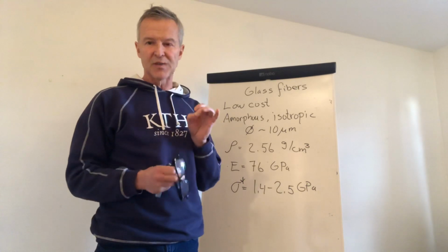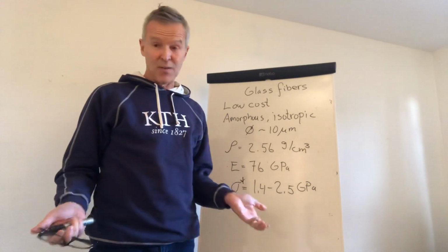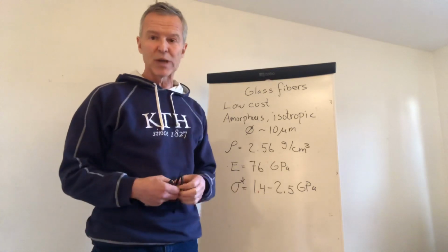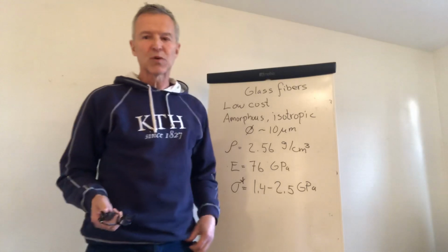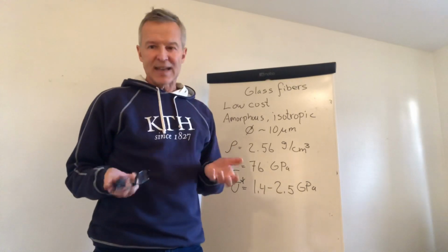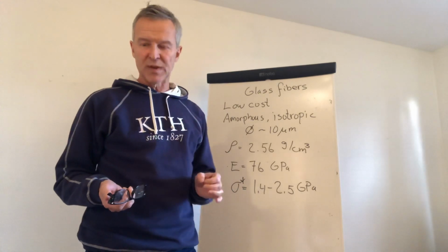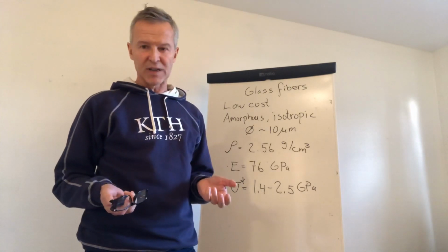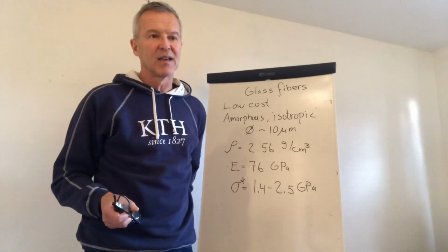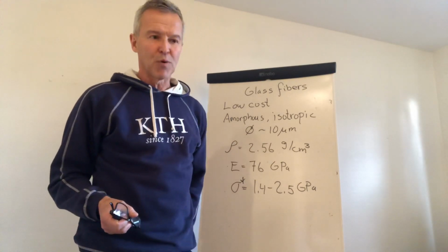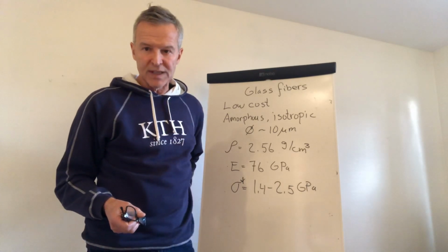So the intrinsic strength of the fiber is vastly increased. The modulus is the same as it is in window glass. So this, I think, is important because it also means that since glass is a very brittle material, this surface smoothness of the fibers is very important. If we have damage of the fibers because of some mechanical handling problems, then the average strength of the fibers will be decreased.